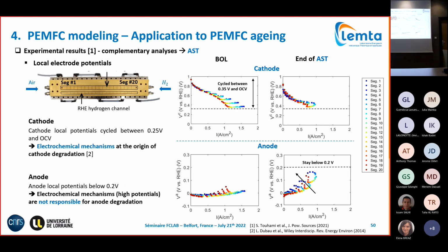But when we look here at the anode potentials, between the beginning of life and end of life, we observe a small increase of the anode potentials, but they always remain lower than 0.2 volt. So it means there's no carbon corrosion. It's not possible. So the decrease we observed in the electrochemical surface area and in the performance could be linked to chemical degradation, perhaps, but not to corrosion.